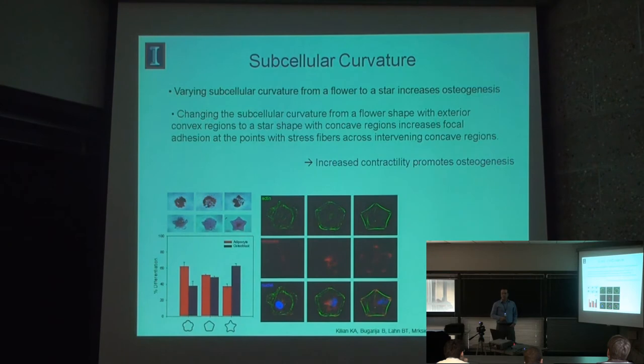Similarly, we did the same thing with a five-fold symmetric geometry, where we have a flower-shaped cell, with these convex regions of curvature on the perimeter, and then a simple pentagon, and then the star-shaped geometry. Looking under a microscope, at first they all look the same, and so this was really startling when we first made this observation.